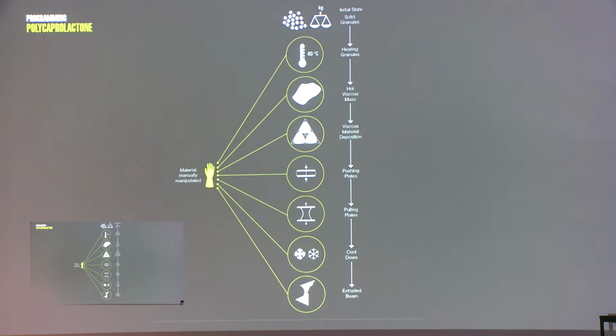So having that in mind, we start to program our polycaprolactone. The first experiments that we did, we used the solid granules, heating them to 60 degrees, getting the hot viscous mass. This viscous mass was deposited in 2 acrylic rigid plates, that then were pushed inwards and then pulled outwards, reaching a length, cooling it down to get a pulled beam.